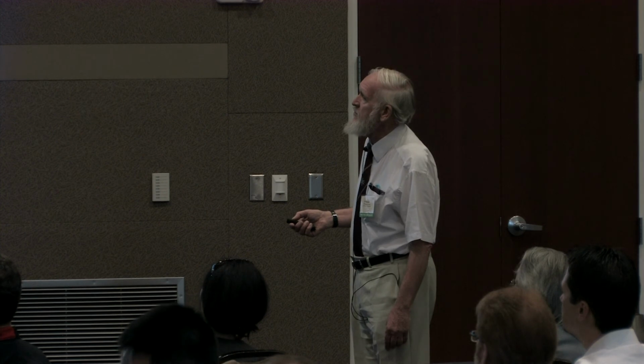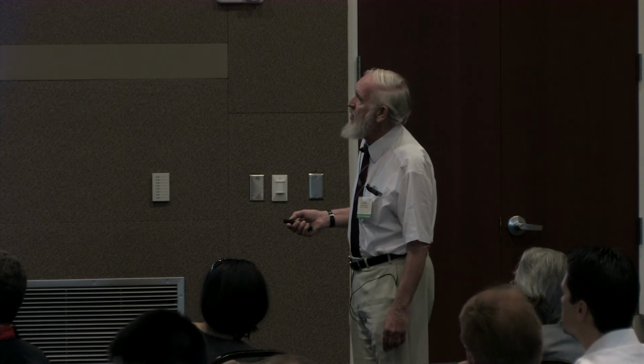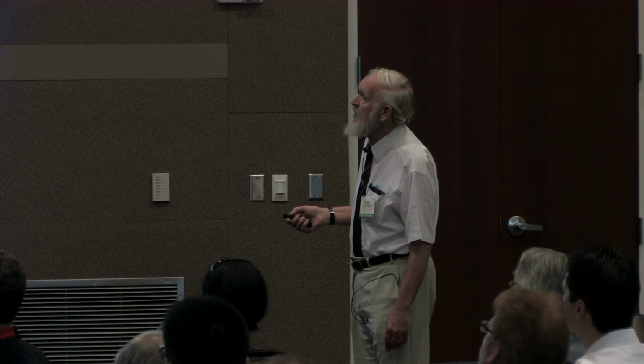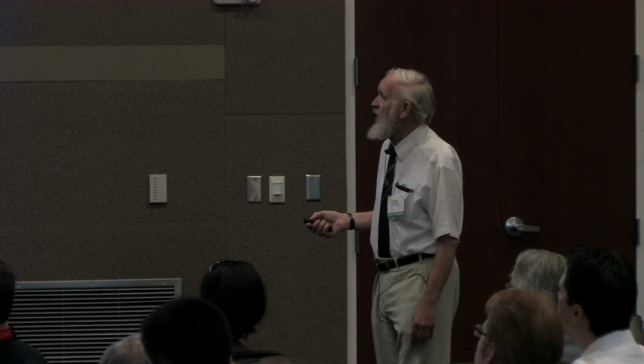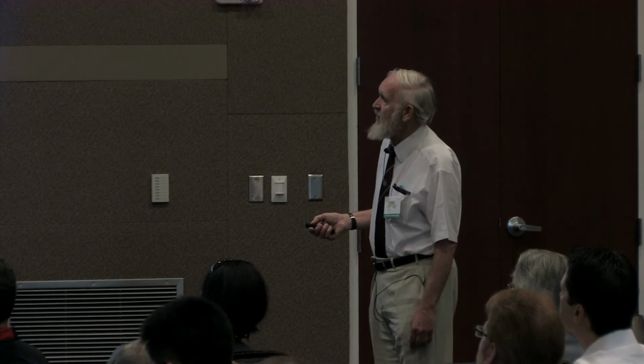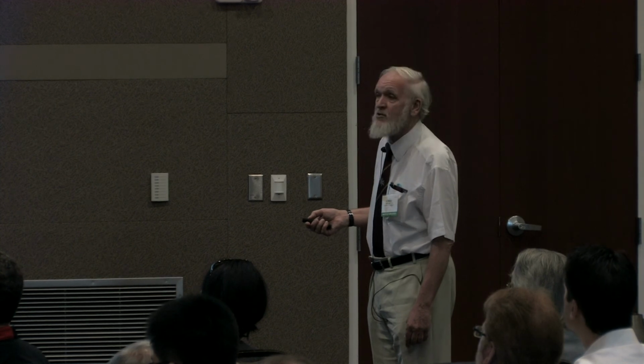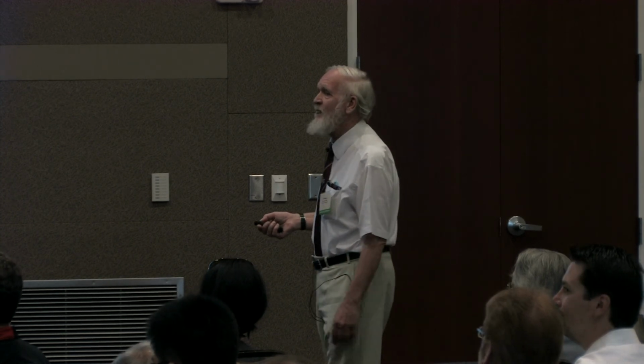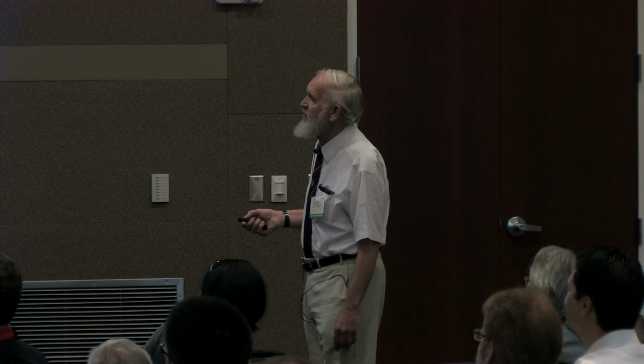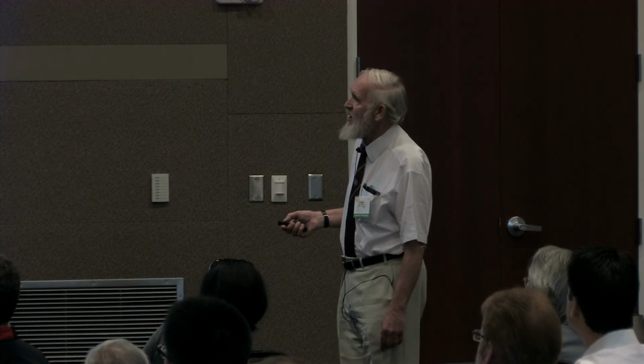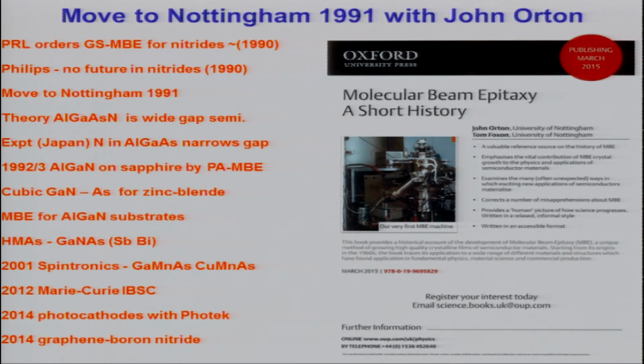So then we went on to look at aluminium gallium nitride on sapphire by plasma MBE and do that work for quite some considerable time. Curiously, one of my colleagues here, Sergey, who's somewhere in the audience with all the hair, has been very patient in growing aluminium gallium nitride substrates by MBE. It takes hundreds of hours, but you can do something unique with MBE that you can't do with any other technique. You can actually grow mixed aluminium gallium nitride of any composition.